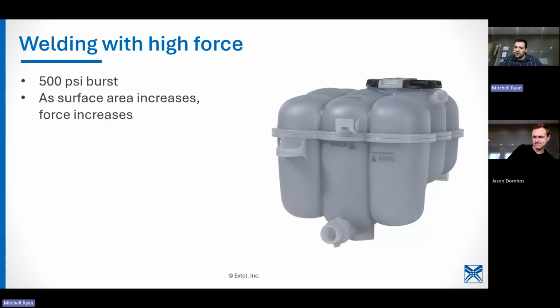Kevin May's question: what wall stock is needed to achieve 500 PSI? Great question. It's all material specific, but you can typically expect probably around 80% parent material strength of that wall thickness when you're welding with hot plate welding. Now, the pressure you place on that joint maximizes that force. In certain instances, if you don't get enough pressure into the weld joint, you could be around 50% parent material strength or even 30%. To get up to that 80% parent material strength, you'll need the higher pressures. But that's typically what we look at, around 80%.